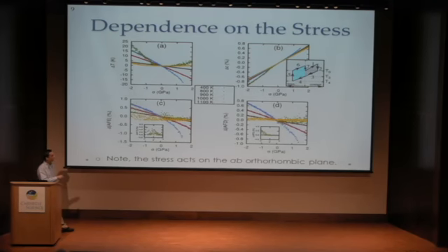We can drain the heat into a heat sink, decrease our temperature, and then adiabatically remove the compressive stress. From here, we utilize the negative change in temperature under tensile stress, which gives an even larger overall change in temperature for this refrigeration cycle. So it's very good for applications.